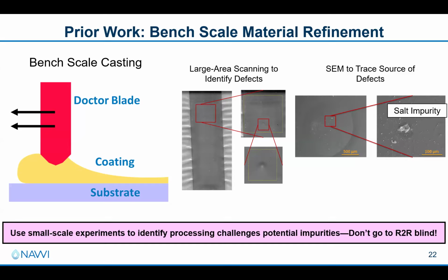In this case, this was casting a cation exchange membrane onto a PET substrate. What you can encounter is that impurities present during the synthesis process, which you would typically figure out how to design your purification process around when you go to scale up, can start to cause challenges when you're initially trying to get this kind of formulation into a roll-to-roll system for membrane manufacturing. Due to the presence of some of these impurities, you can get things like pinholes that reduce your ability to actually implement this kind of membrane in a real device.